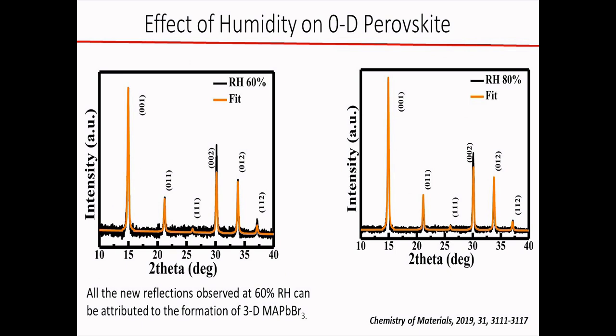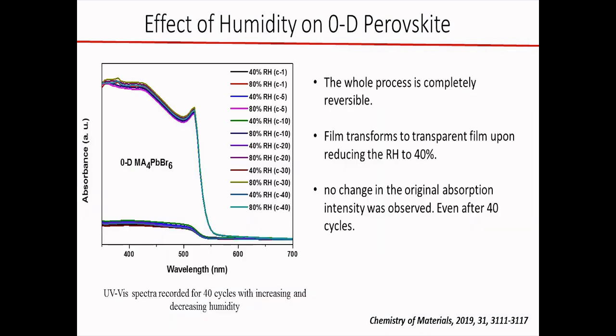This is also confirmed from the X-ray diffraction pattern, where at 60% RH we have complete transformation to the 3-dimensional perovskite, which is MaPbBr3 that is formed. This process is completely reversible.